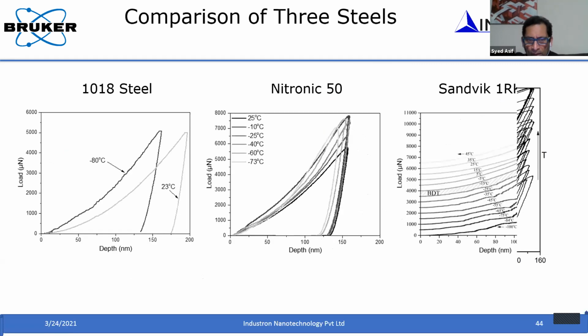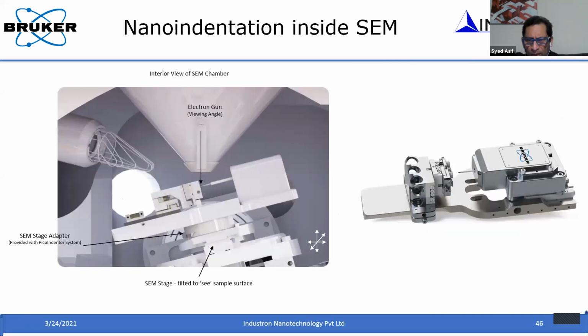Okay. So same thing for a different steel. I just wanted to quickly give an idea. You can do the same experiments inside a scanning electron microscope, and you can do that XPM analysis. It wasn't available a few years ago, but recently we introduced this functionality inside the SEM. So now we can do these experiments inside the SEM. I can directly go and check that with the EBSD to get the EBSD map. If you have the rotation and tilt stage, instead of just the linear stage that I'm showing over here, you can do this indentation experiment, or you can go to the EBSD detector, do the map, bring it back to the indenter, and then do the indentation experiment.